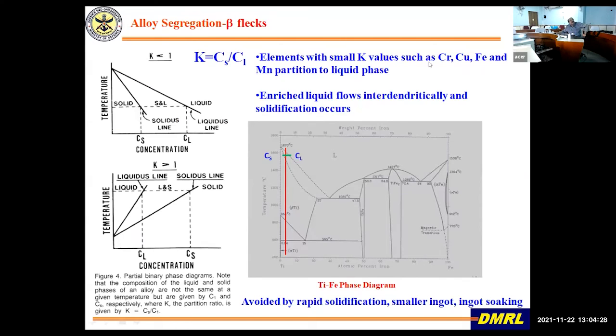Now, elements like chromium, copper, and iron, etc., have a partitioning coefficient less than 1. What is a partitioning coefficient? Suppose you have this alloy solidifying, and this is the phase diagram. At this temperature, this is the composition of the solid that solidifies, and this is the composition of the liquid. If you divide this composition by this composition, this is known as the partition coefficient. If this is less than 1, then as you cool, because industrial solidification is a non-equilibrium phenomenon, this type of alloying addition gets rejected into the liquid and it segregates.